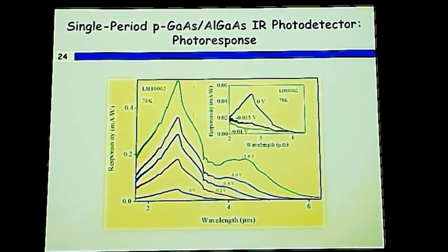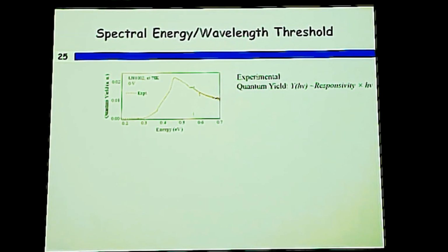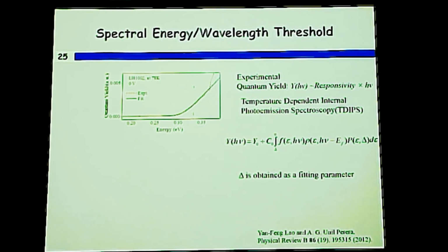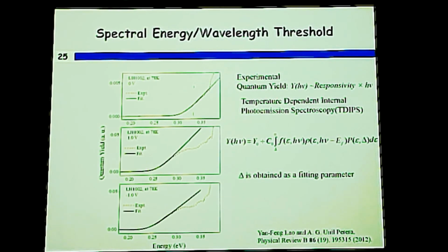Now that we have photo response, we want to see what is the threshold energy or threshold wavelength. And we look at the quantum yield. This is the experimental quantum yield, which is proportional to responsivity multiplied by the energy. To find the threshold, we are interested in this region where there is a threshold. So we apply a fitting. The method is called temperature-dependent internal photoemission spectroscopy. Based on this fitting, this energy is obtained as a fitting parameter of the fitted curve. And this is for zero bias. We can do it for all different biases.